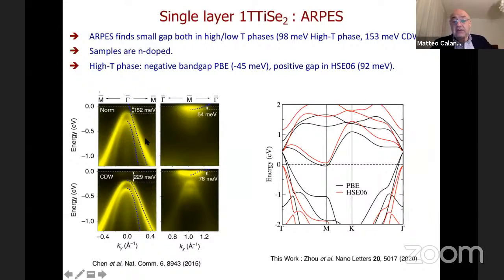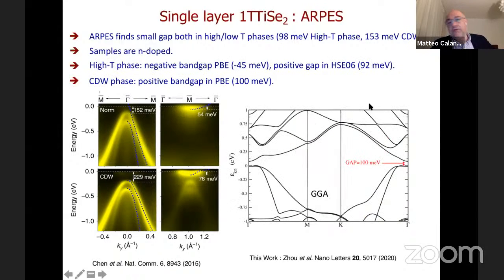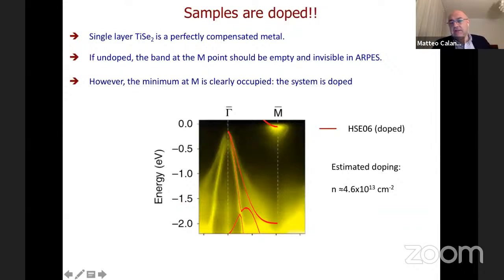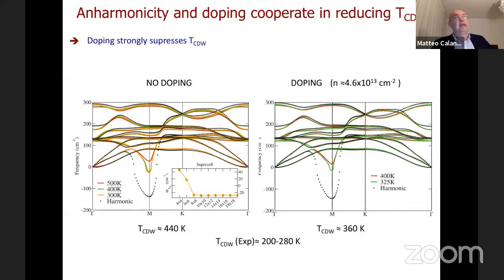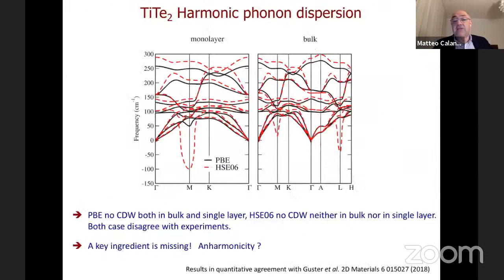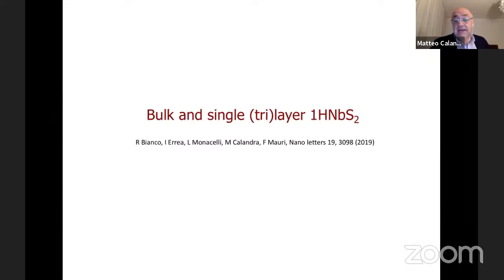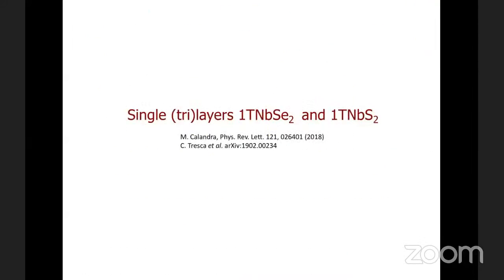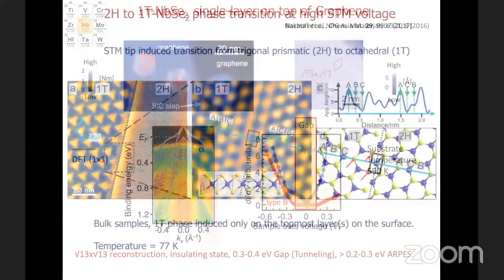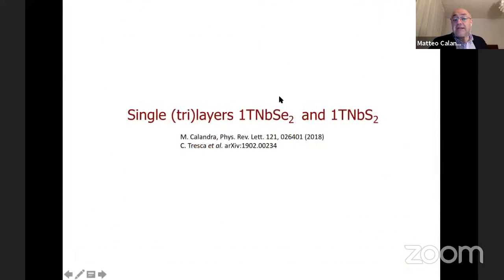Now there are other kinds of dichalcogenides. Let me show you. The classical example is 1T tantalum disulfide, in which there is a very flat band. I didn't do this calculation, but in this case, most likely, the electron-electron interaction is very important. Another case where it is very important, and it's very similar to tantalum disulfide, is 1T niobium diselenide, which was synthesized very recently.